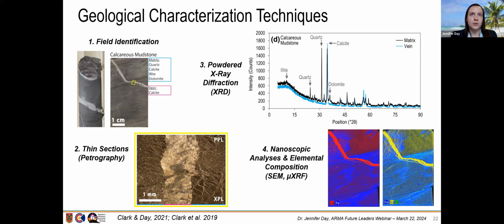We also looked at characterizing these rock samples geologically, so looking at field identification and those types of observation skills, thin section and petrographic analysis. We also employed X-ray diffraction to look at the crystallographic mineralogy. The XRD was powdered in a bulk format, and we could separate the sample out between matrix and vein. And then we also looked at spatial mapping using scanning electron microscope and micro X-ray fluorescence to look at the elemental composition across the thin sections as well. So spatially, we could have a look at some of those characteristics geologically.